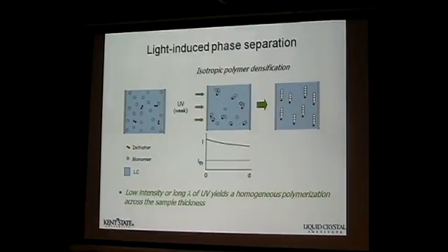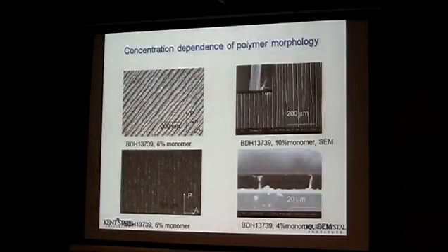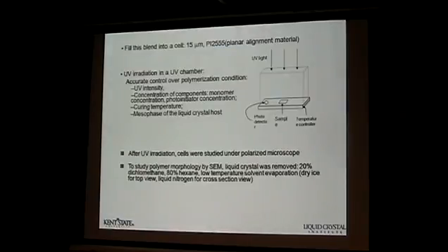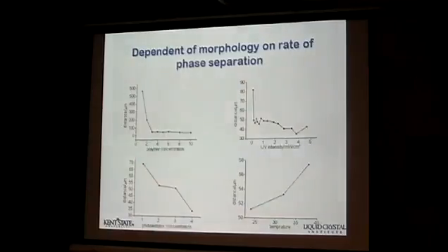So that's the cartoon here, and so we skip this. In general, if you have alignment of the cells, and then you control the UV light condition, these cells form kind of fibril-like structures from the top of the substrate, at a polymer concentration of roughly 6%. You increase that to a higher concentration, and you see a denser network. In fact, this is only surface alignment. And you can see that periodically they form very nice fibrils connecting the top and bottom substrates.